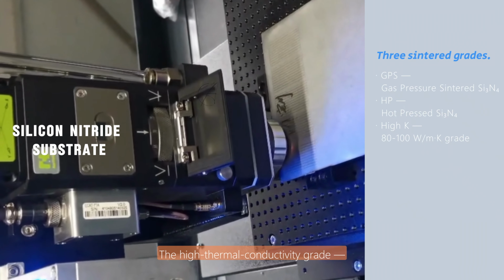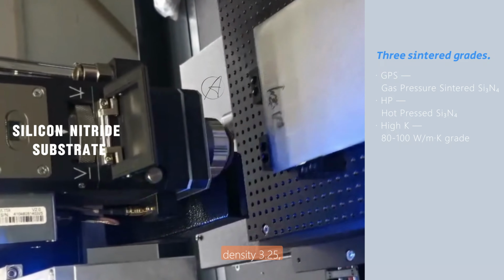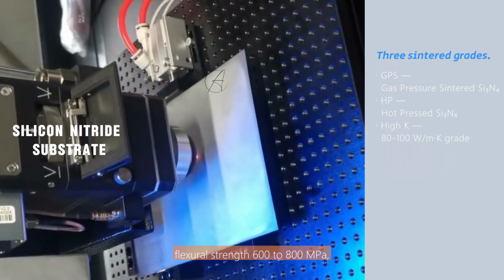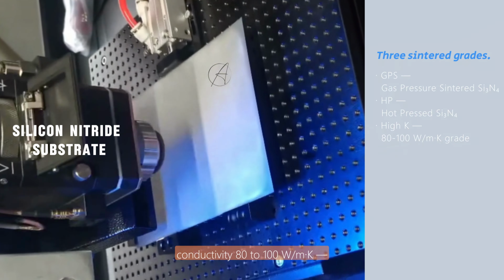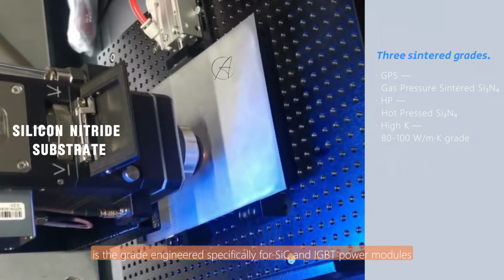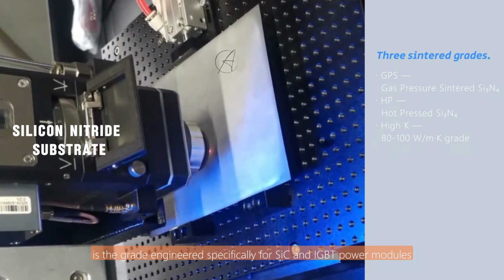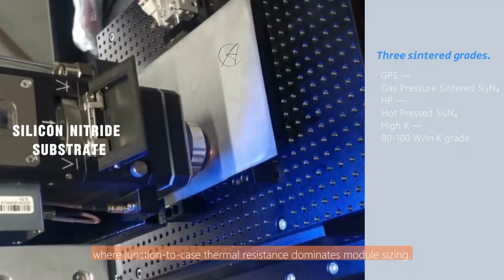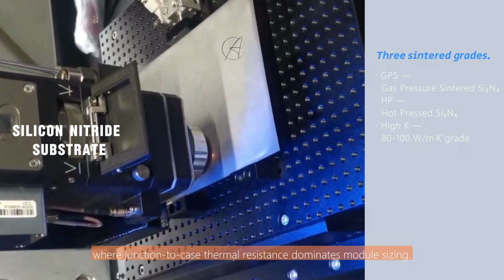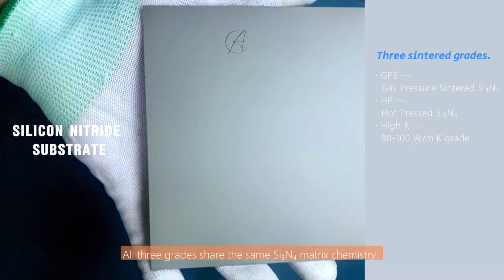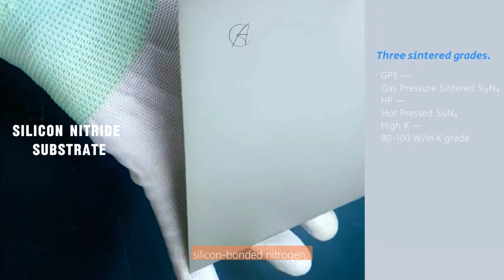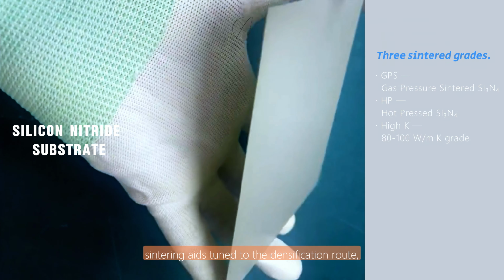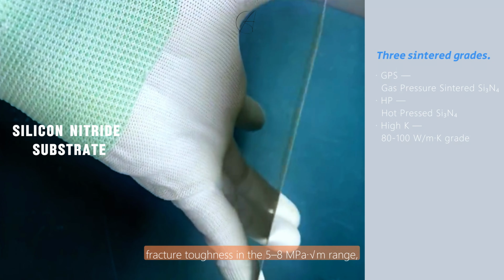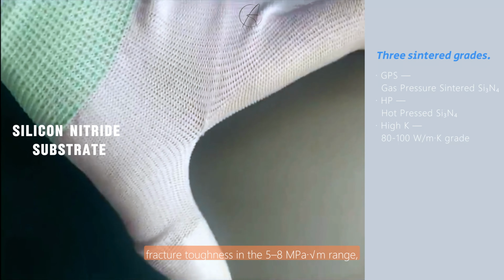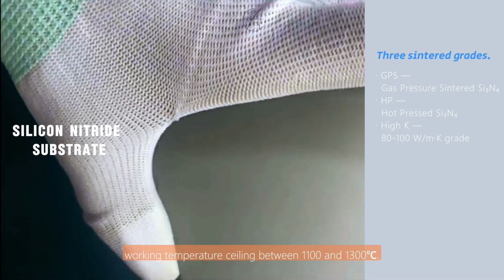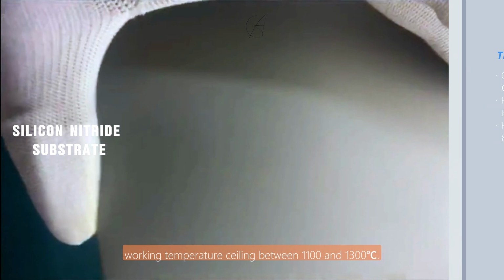The high thermal conductivity grade, density 3.25, flexural strength 600 to 800 megapascals, conductivity 80 to 100 watts per meter per Kelvin, is the grade engineered specifically for silicon carbide and IGBT power modules where junction-to-case thermal resistance dominates module sizing. All 3 grades share the same silicon nitride matrix chemistry. Silicon-bonded nitrogen, sintering aids tuned to the densification route, fracture toughness in the 5 to 8 megapascal root meter range, working temperature ceiling between 1100 and 1300 degrees.